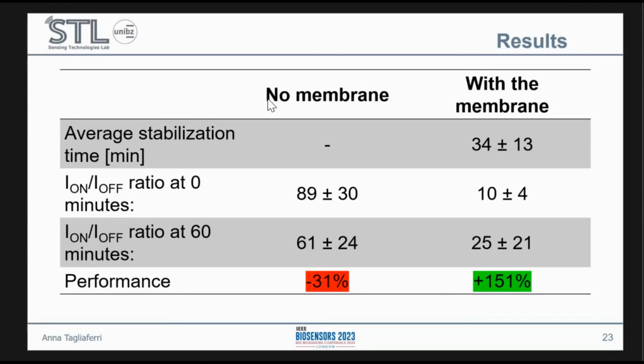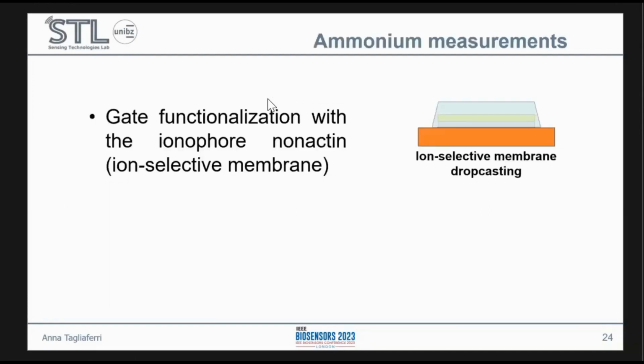Just to give a little recap of our results, we cannot really say that the devices with the membrane reach a stabilization point. They reach a linear trend over time, but not really stabilization. In our case, we reach this linear trend in 34 minutes, which is approximately half the time that state-of-the-art devices fabricated with polymer-coated carbon nanotubes exhibit. Also, the improvement in performance is really outstanding. We can see a decrease in the performance without the membrane encapsulation, and we see a 151% improvement in our devices.